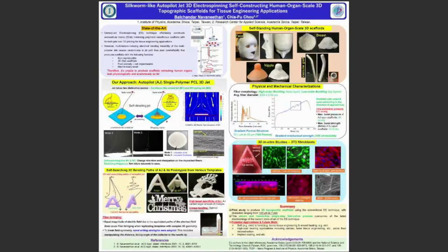And so this mode can actually expand this area and the thickness of the scaffold in concentric circles. Because when you use the 3D collector as a template, the electric field is highly non-uniform, prior studies were unable to achieve conformal fiber deposition. However, when we used a 3D collector just like this, we were able to achieve 3D conformal fiber deposition to have 3D scaffolds.